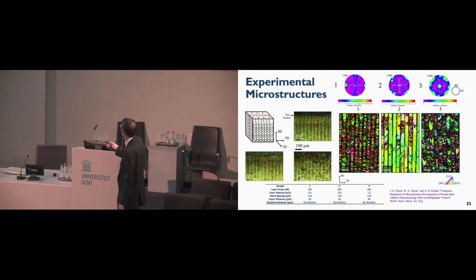I'll look at this one in the center: there are long, skinny grains. And then in between, there are really quite coarse grains, and clearly with a different texture. So you have a mixture of the texture that you might expect, 100, because of the preferred growth direction, solidification direction, and something that I didn't expect, which was 110 texture. So where the heck does that come from?